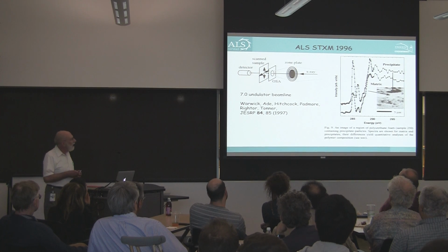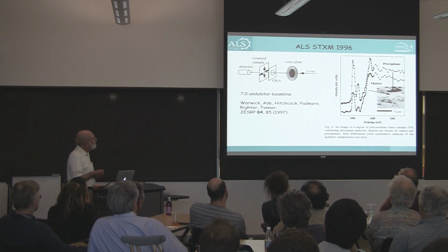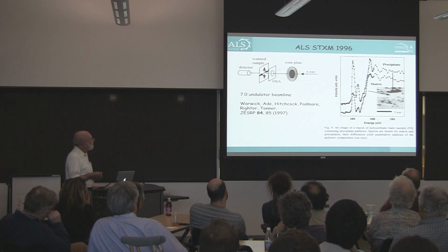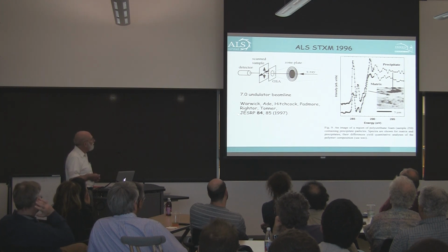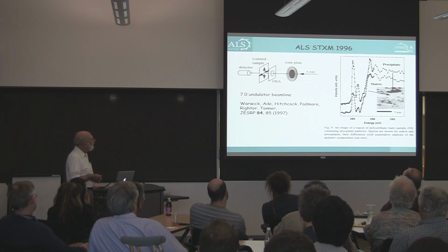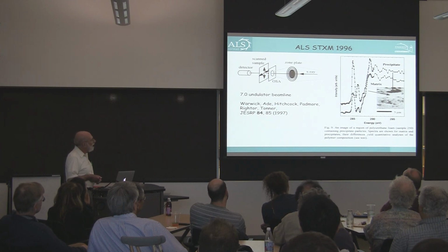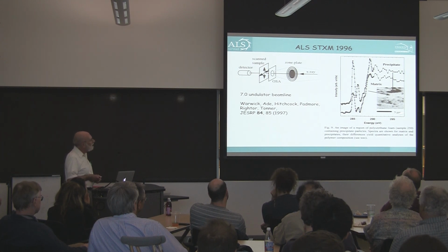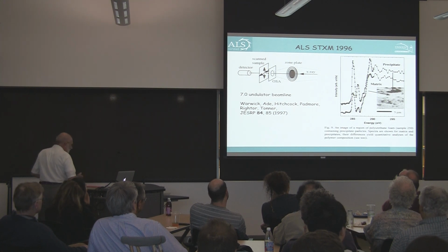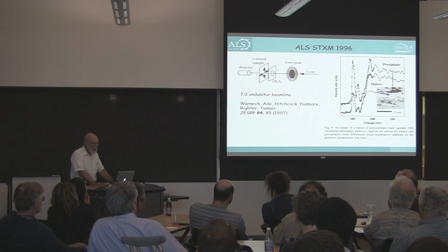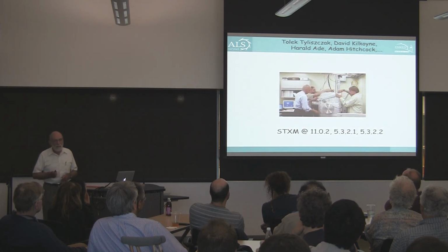Not long after that came the first scanning transmission X-ray microscope at the ALS, and the first publication from that I found was by Tony Warwick, Harald Ade, Adam Hitchcock, Howard Padmore, and collaborators in the Journal of Electron Spectroscopy and Related Phenomena from 1997. They were looking at a slice of polyurethane foam and found that they could image it at high resolution and find the spectra from the different areas, so they could pinpoint what chemical components were present at the different places.